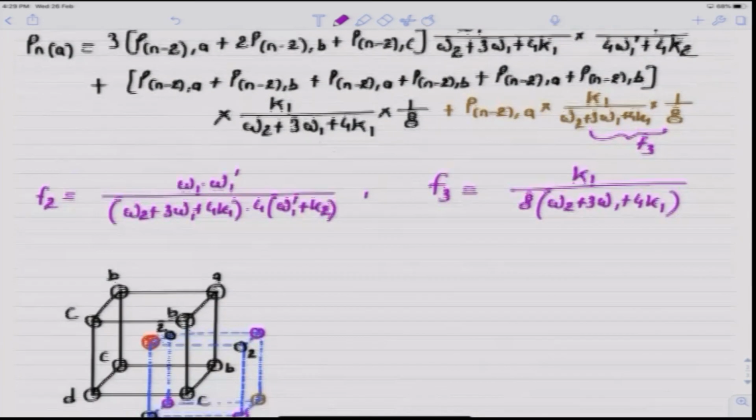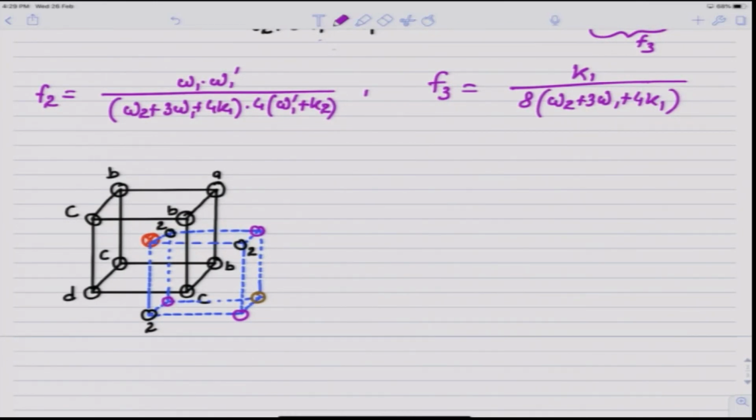Let us now consider Pn of B, that is the probability that the vacancy arrives at site B after making n jumps. So, I have shown the type B site. Let us consider this type B site here. I have also shown all the nearest neighbors of this type B site here, out of which there are 2 second nearest neighbors of B, shown by number 2 here, 3 are third nearest neighbors, and 1 is the fifth nearest neighbor, it is shown by number 5 here.